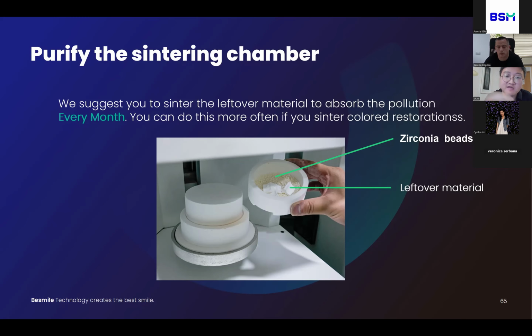It's better if you can use white blanks, because white blanks after sintering are supposed to be white. If there are other colors like green or yellow, it means the chamber of the furnace is polluted. In this case, you need to use this leftover material to purify the sintering chamber several times until the result appears white.